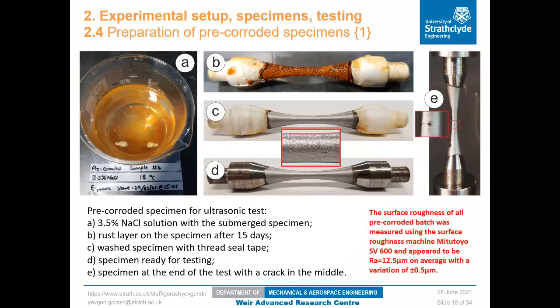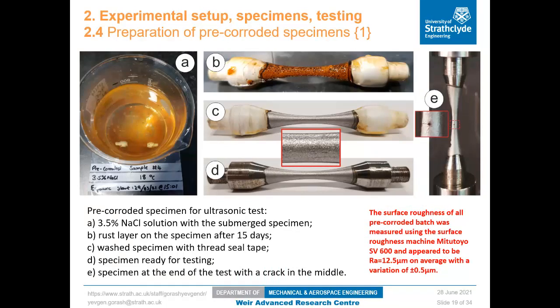Apart from the samples with ideal surface finish, there were also two batches of samples. They were pre-corroded in a standard 3.5% sodium chloride solution, and they were submerged in water, the first batch for 2 weeks or 15 days and the second batch for 1 month. After that, the samples were taken from this solution, cleaned of the rust and prepared for testing. The good thing about these samples is that they didn't need any painting, because the emissivity of the surface was quite enough to get correct temperature readings, and also the heat generation was much lower than with the samples with ideal surface finish.